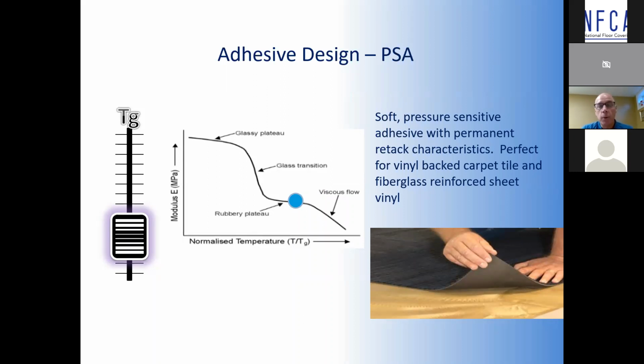Why is that? Well, the luxury vinyl plank has a glass transition temperature, and so does the adhesive. So if you use a PSA with a very low glass transition temperature, remember at service temperature, so at 20 degrees, it stays soft, with pressure sensitive characteristics. However, as the temperature rises, it gets softer. And so as the temperature rises, it can allow the material to start to slide around. That's why glass transition temperature is so important when you're a chemist, because as you're building these materials, you have to know where that temperature is going to end up.